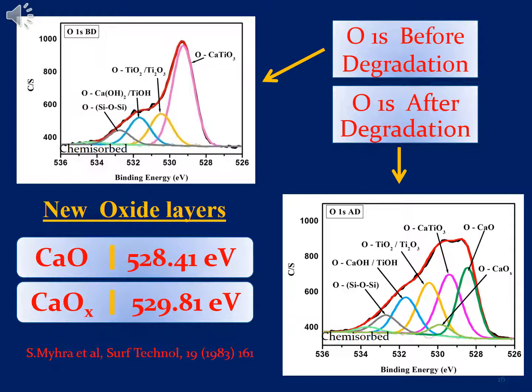Now that reduced ratio indicates to us that we are forming more titanium dioxide, calcium oxide, calcium hydroxide, and the others. Now, we can clearly see from this that we have formed new oxides, and they are an agent for quenching our luminescence intensity.